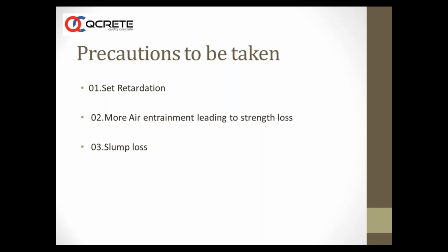So they were abundant. But there are many other cases where set retardation has taken place for 24 hours and the strength gain has happened after 7 days and 28 days. In many of these cases where set retardation has taken place, surprisingly, the concrete which has retarded has gained strengths higher than normal concrete, or more than what it would have gained if it had set normally.